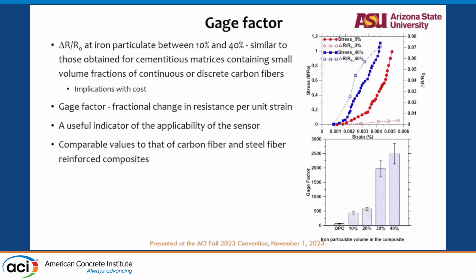So how this translates is, at one point we introduced another factor called gauge factor, that basically is the ratio of delta R by R naught divided by the strain percentage. So the higher the gauge factor, the more significant response we see on a small strain change. So you see a higher delta R based on a very small strain change. What it helps to do is, you don't have to be too accurate.